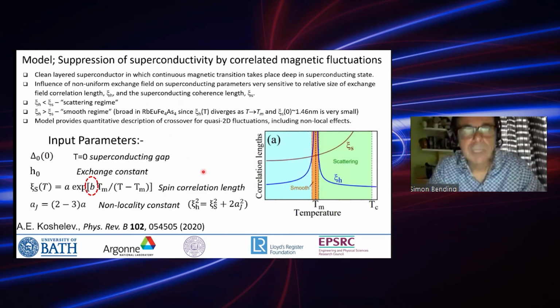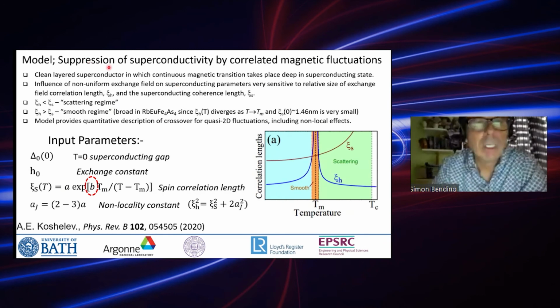So how can we understand this behavior? Well, to try and understand it, we have compared it with a model of the suppression of superconductivity due to 2D magnetic fluctuations, which was developed by Alex Koshelev, described in this paper here. The model makes a number of assumptions which are listed here. So we're assuming we have a clean layered superconductor in which a continuous magnetic transition, essentially a 2D BKT type magnetic transition, takes place deep in the superconducting state.